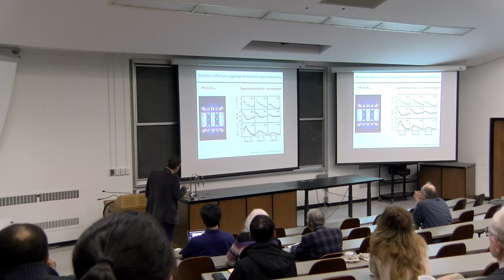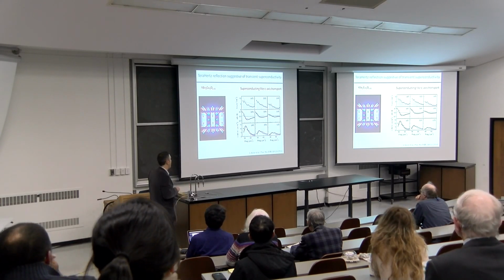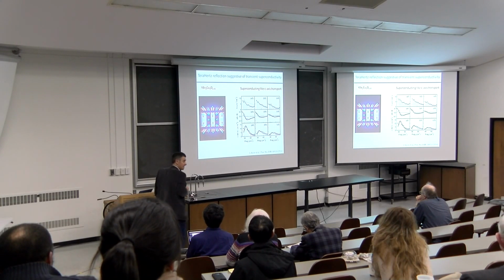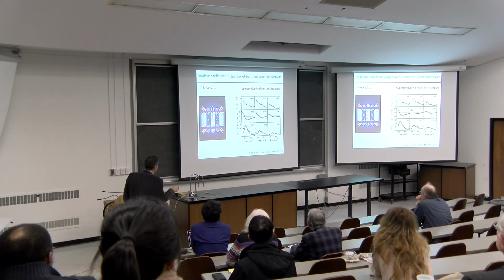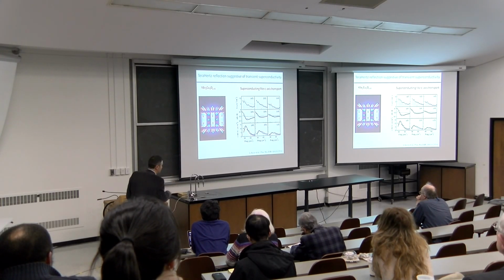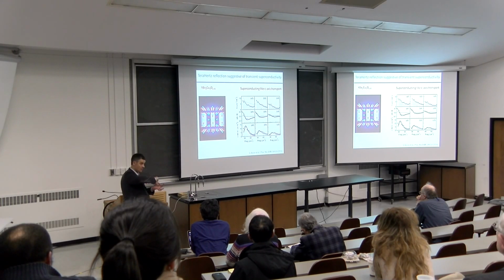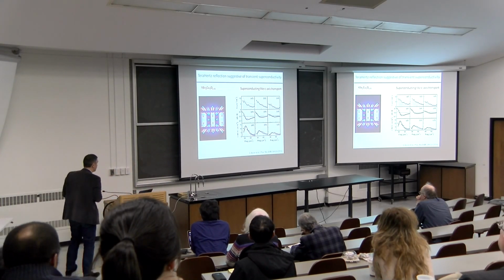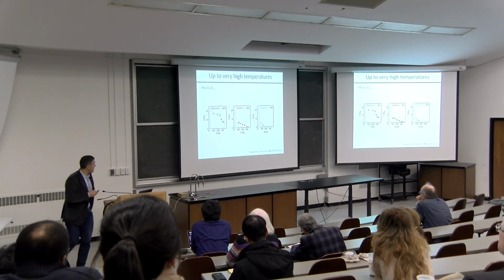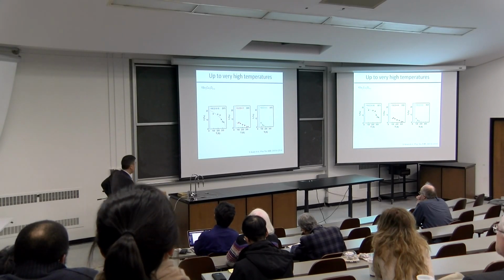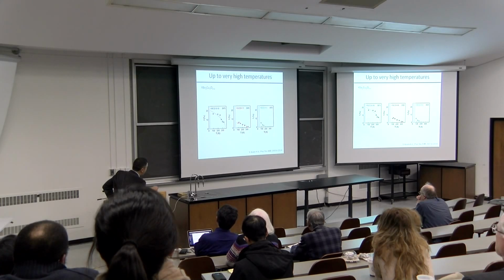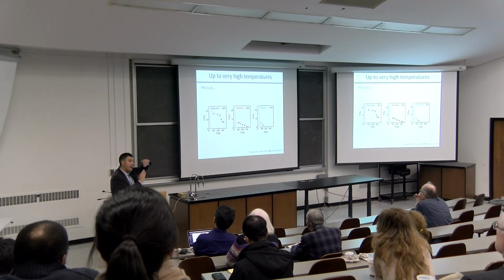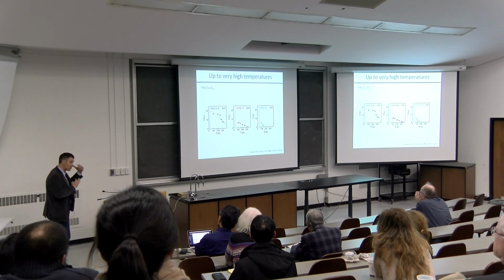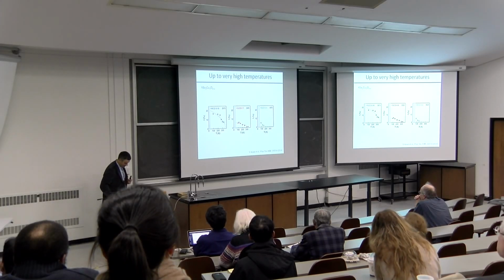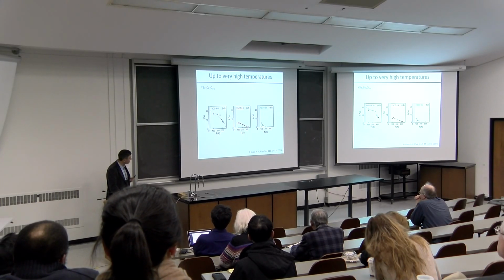And then again, a plasma edge, more or less in the same position where one finds the same plasma edge by cooling the material. What was striking is that one could observe this up to... this is the loss function I wanted. This is basically the inverse of the real part of the dielectric constant. This tells you that the dielectric constant is crossing 0 at that frequency, so the inverse has a peak. So what was striking was that one could find this light-induced effect up to extremely high temperatures. And in fact, as a function of doping, up to the edge of the pseudogap phase, this mysterious phase that looks almost superconducting but is not superconducting, could be changed in a way that was suggestive of superconducting fluctuations.